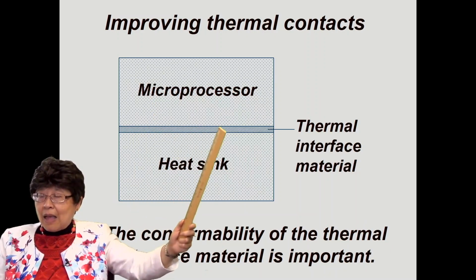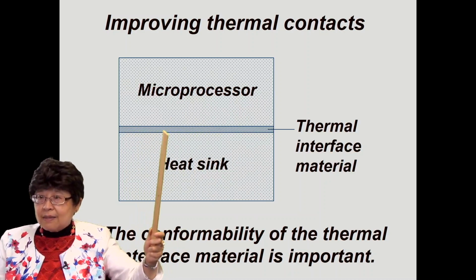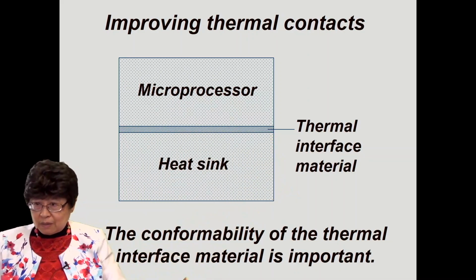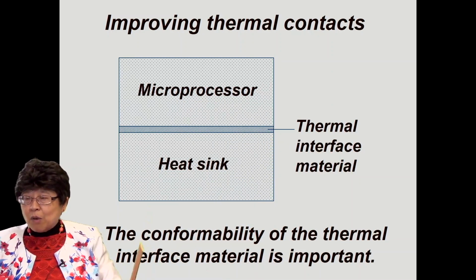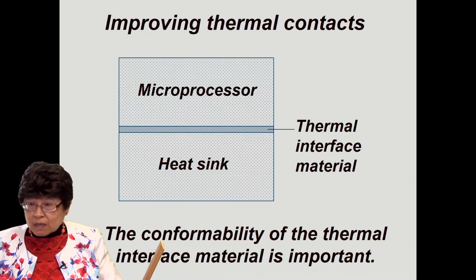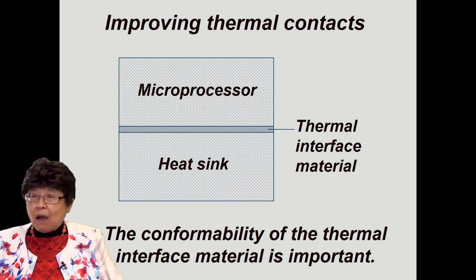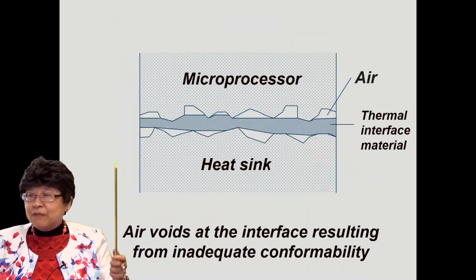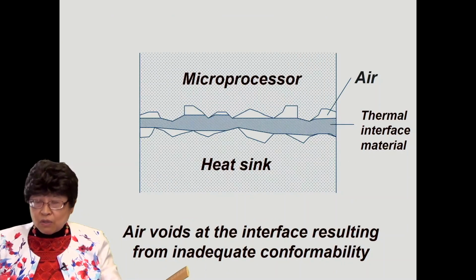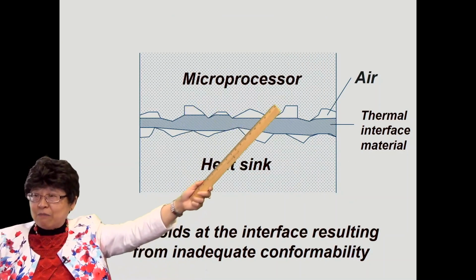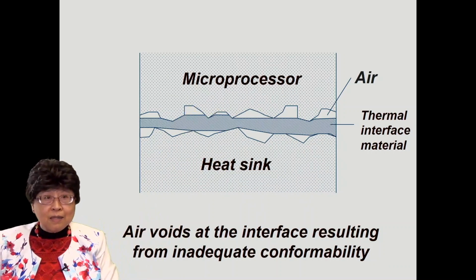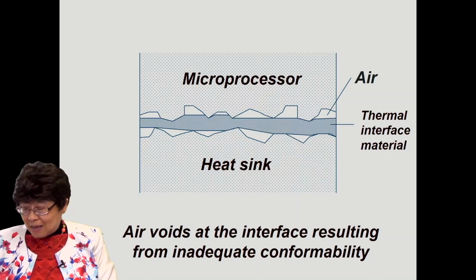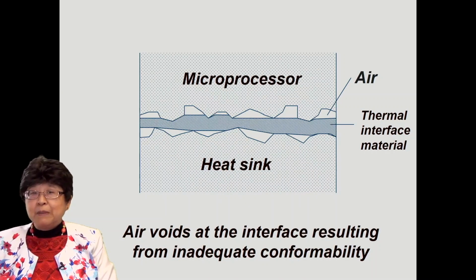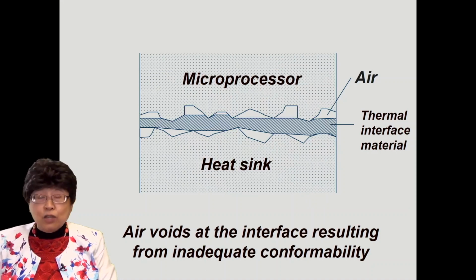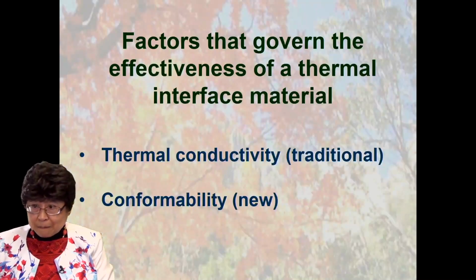And in order to improve the thermal contact, one puts in a thermal interface material. The thermal interface material needs to be very conformable to the surface topography of the two mating surfaces. If the conformability of this thermal interface material is not so good, you would have some air pockets left behind at the interface. And air is a thermal insulator, and so that's bad. So you've got to have the thermal interface material be very, very conformable. Having this interface material be just thermally conductive is not good enough. One has to have high conformability.